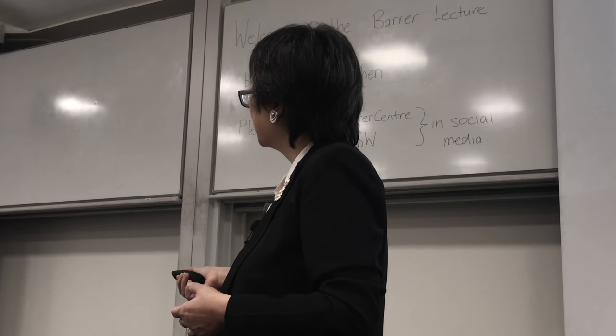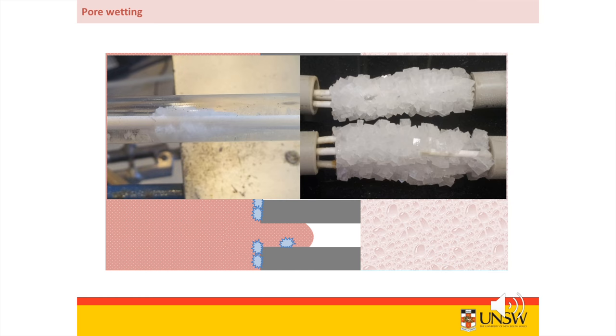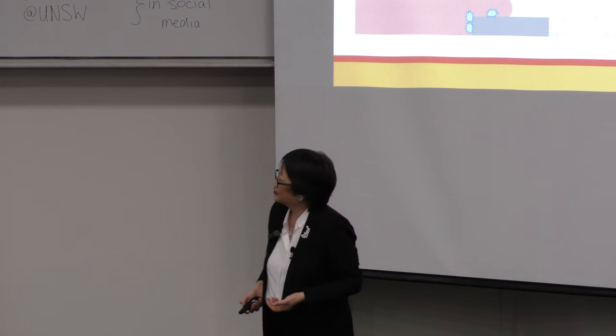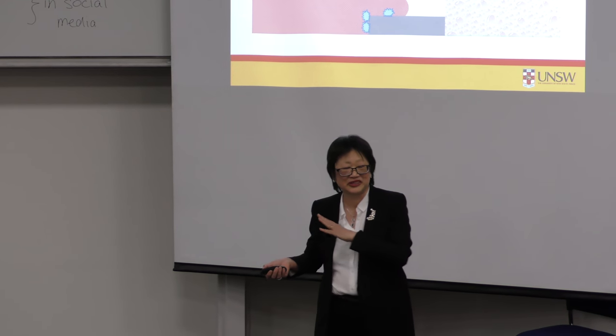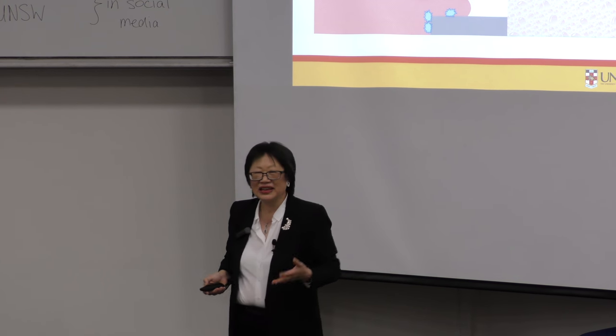Now, the problem is, of course, wetting and fouling is still the issue, because as we increase the concentration to very high degrees, we could get scaling, we could get wetting. So we look closely at the interface. As we increase the concentration on the feed side, we get precipitation, especially divalent salts. And of course, that hydrophobic membrane will eventually wet out, then you get contamination. It can be as severe as getting full-on crystal growth. In fact, these membranes still survive, which is pretty incredible if you think about it. These membranes are recoverable. But how do we actually overcome that?